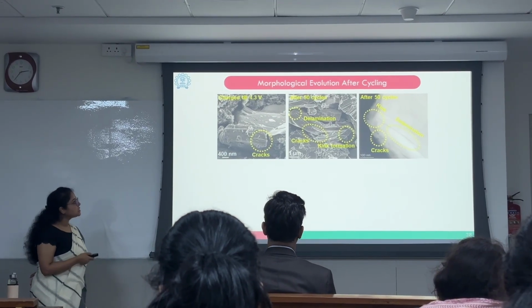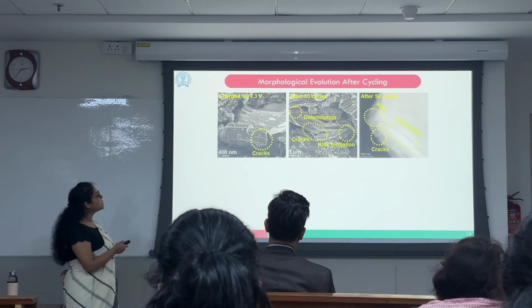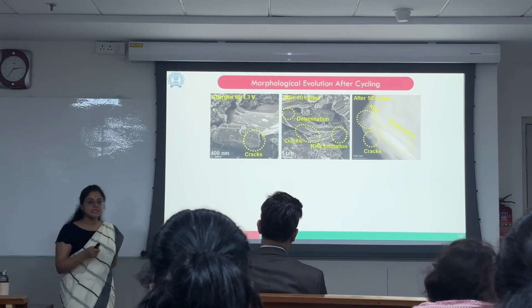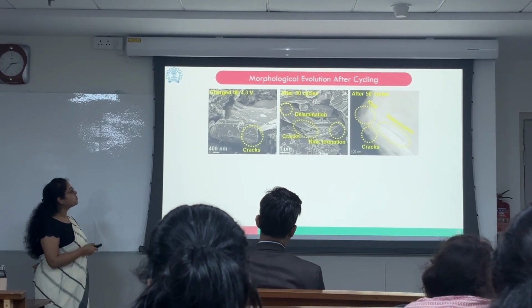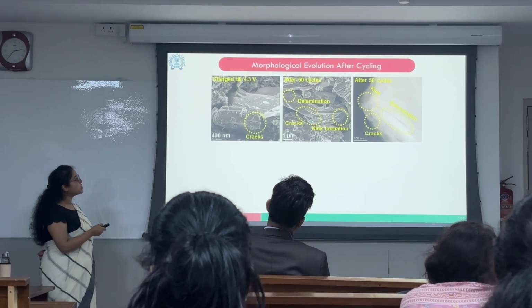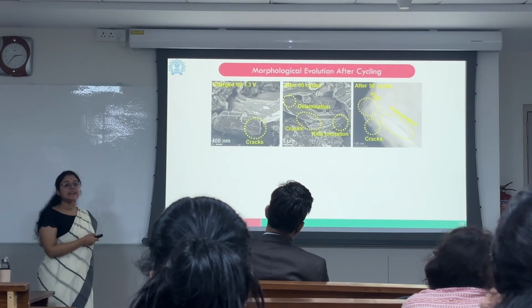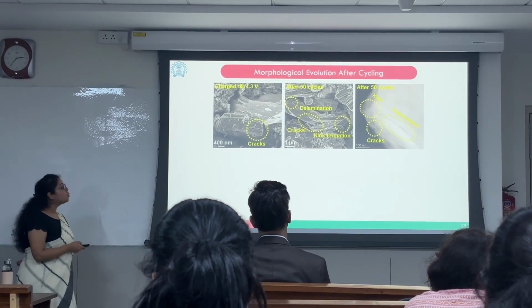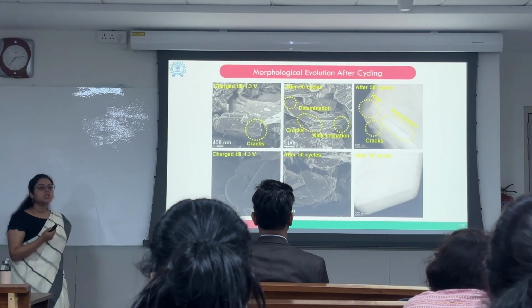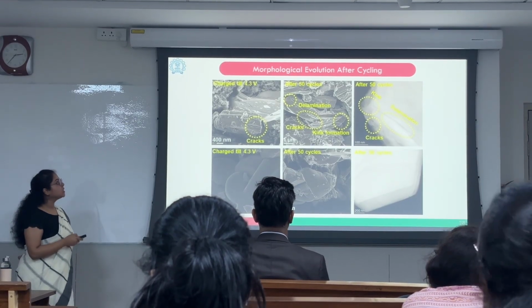So the morphological evolution tells us that the pristine particle, when charged at a higher C rate till 4.3 volt, gives us cracks and exfoliation, which is also visible through high angle annular dark field imaging, which was absent in the case of the ruthenium doped cathode material.